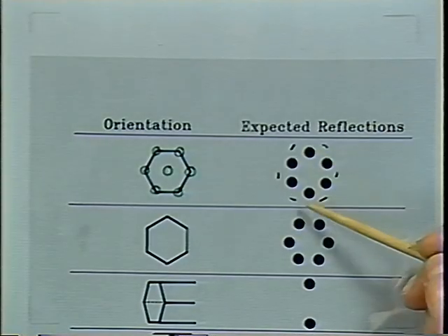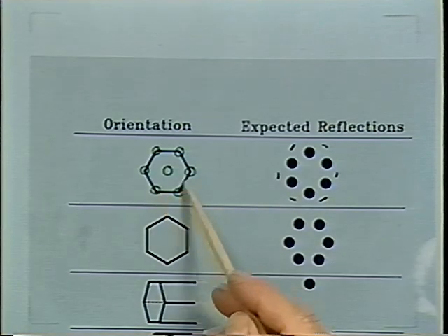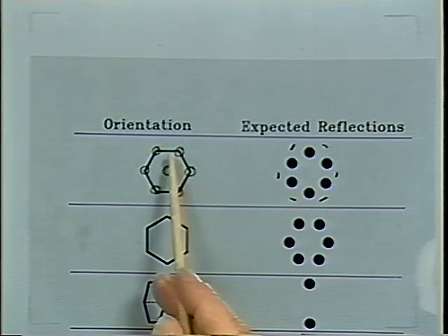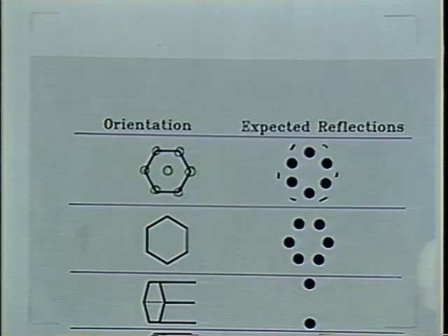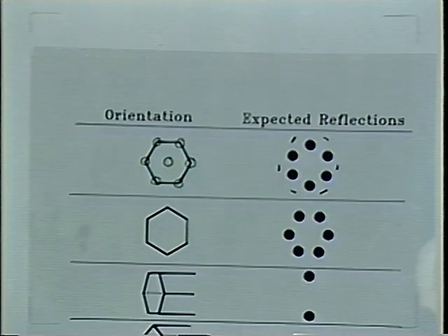So when the reflections are top and bottom, we have hexagons which are aligned like this, and the plane of this is parallel to the plane of the sample. We don't know why this occurs, but it's quite an interesting observation that those hexagon planes are aligning.